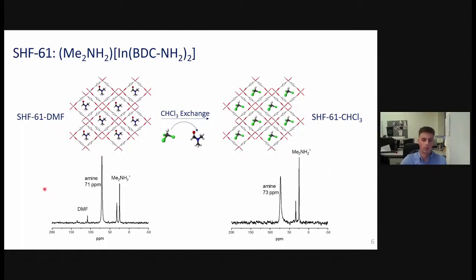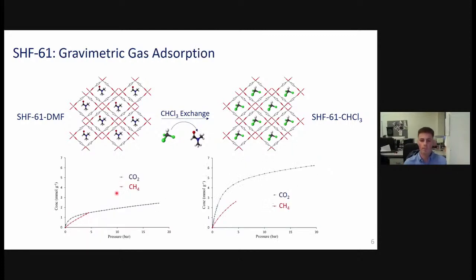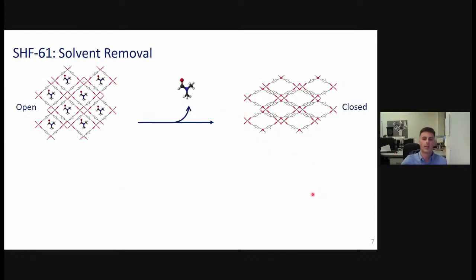But we've also shown that this is the case in the bulk phase of the material. We use a number of different techniques, but I've shown here some solid state 15N NMR, which nicely shows that full conversion of the solvent. So if you're able to remove that residual solvent from the pores of the framework whilst maintaining the structure, or at least keeping some permanent porosity, then you can start to look at reintroducing gas in the form of gas adsorption. What's interesting about this material is that the framework has two very different adsorption isotherms, depending on whether you activate the material from DMF, on the left here, or whether you activate the framework from chloroform on the right. The reason for those different isotherms lies within the behavioral response of the framework to the removal of those guest species.